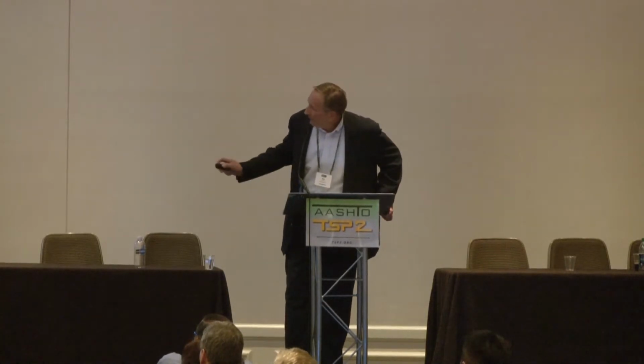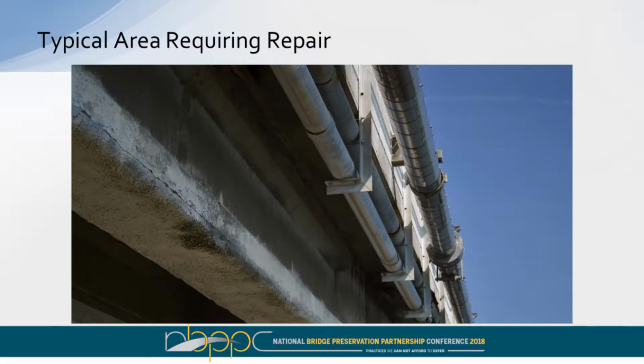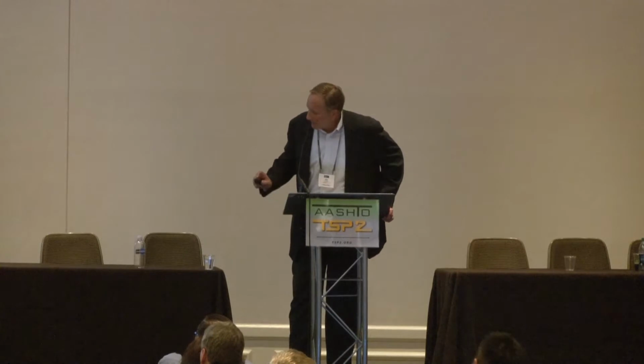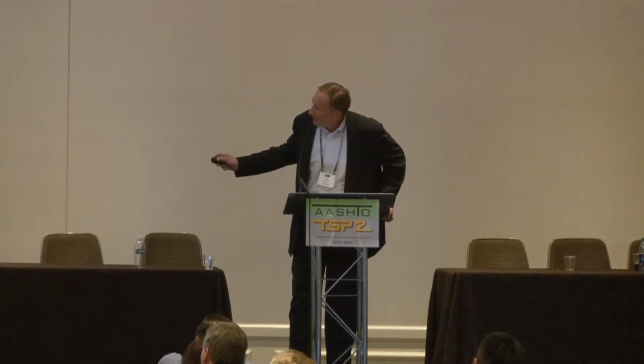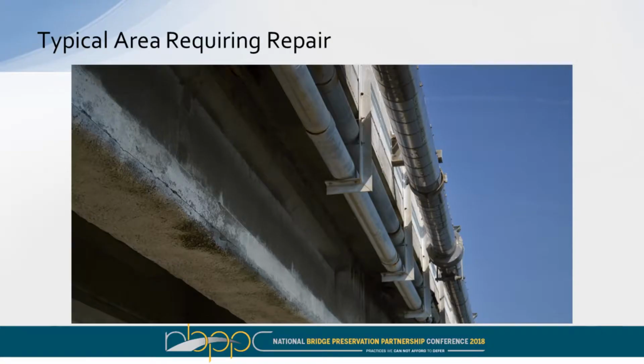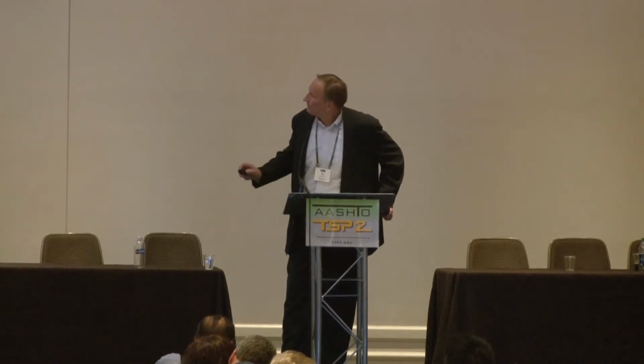And from this particular slide, in addition, you can see, in this case, back several years ago when they performed the last repairs on this, there was a 2-inch layer of gunite that was applied to the underside of the flanges for some reason, which I don't know. And in this particular case, and in most cases throughout the structure, you could see where there was cracking that was occurring between the interface. So not sure how it was applied, but of course, perhaps the original intention of thickening that up, maybe giving it some more load carrying capacity, in this particular case was starting to fail because of the cracking.